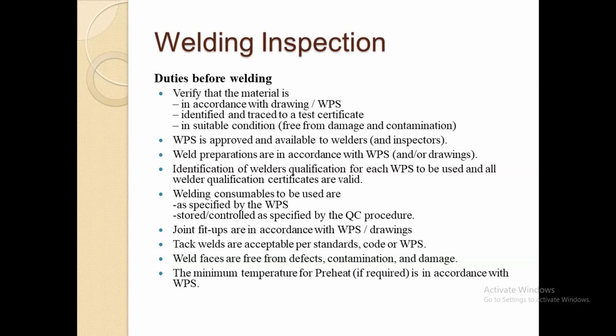The inspector has to make sure that the welding consumables are as specified by the WPS and that they are stored and controlled as specified by the qualification quality control procedure. We have a serious challenge with that part, especially when it comes to the use of low hydrogen electrodes. And the common one we use here is the E7018 electrode. It is a fight getting contractors and workers to store these electrodes and handle them properly.